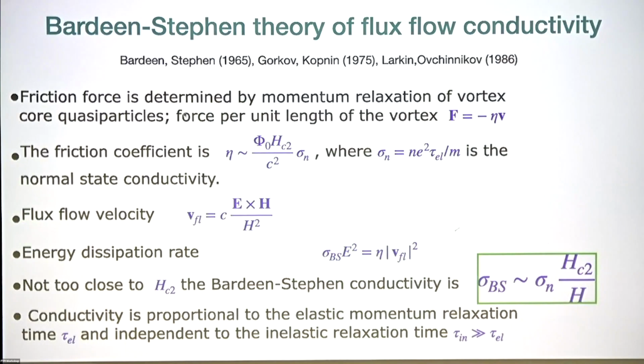This consideration of the flux flow conductivity was originated by Bardeen and Stephen, and then many other people worked on this. In a nutshell, the friction force is proportional to the velocity of the vortex core, and the friction coefficient eta is proportional to the normal state conductivity. It reflects the fact that a core can be considered as a chunk of a normal metal. With this expression for the viscosity, you can equate Joule heat to the energy dissipation rate due to viscous friction. Then substituting the flux flow velocity, one gets this well-known result of Bardeen and Stephen for the flux flow conductivity. It's essentially the normal state conductivity times this ratio of H_c2 to H.